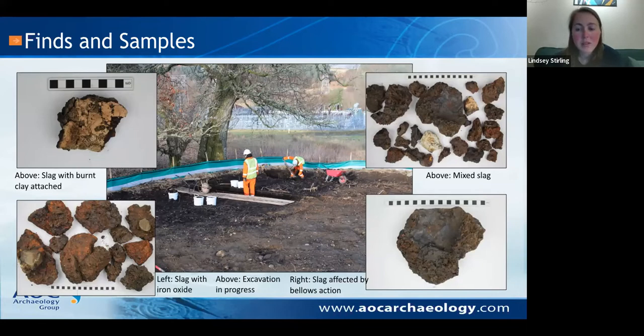Within the slag itself, most of it looks really bubbly, like lava. That's because it's so molten when it's being melted. But we've been finding there are lots of voids within the slag as well. This is where it has formed around pieces of fuel while it was still molten. Hopefully from some of these pieces, we might be able to get some residues of the specific fuel that was used during the processes.